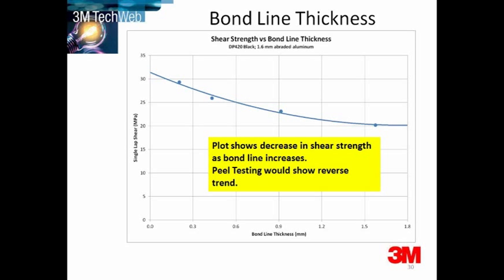So understanding the forces in your joint and the type of adhesive you have is very important for knowing how much to apply. Typically for structural adhesives, around 0.3 millimetres is a good number for joints in shear or tension. If it's in peel, you want to go higher — maybe up to a millimetre.